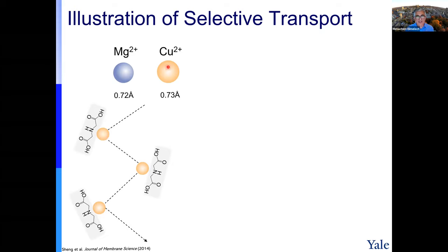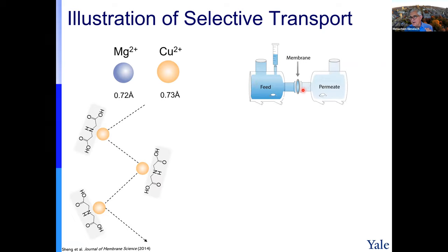And it's well known that copper can bind very strongly. The log stability constant is about 10, and magnesium will not bind to it. So we hoped, and again, we adapted some of the techniques from the literature of the group of Bruening from Notre Dame, that copper will bind here and move like the potassium channel. We did a diffusion cell. We put both the magnesium and copper here and measured the diffusion across a membrane in a diffusion cell.